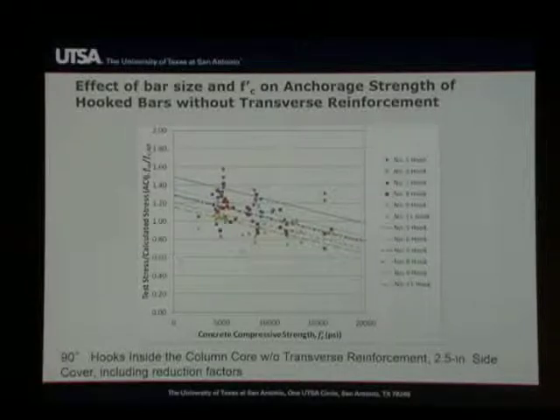Okay, so I'm going to go over experimental results. All the dots that you see are test results. On the horizontal axis, in this case, for example, you have concrete compressive strength. On the y-axis is the measured value of stress normalized by the equation that I just showed for ACI. So in a way, the lines are showing the degree of conservatism of the design expressions that we're using today. Okay? And you see that these lines all have the same slope.